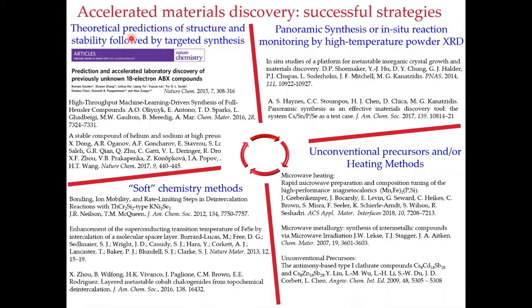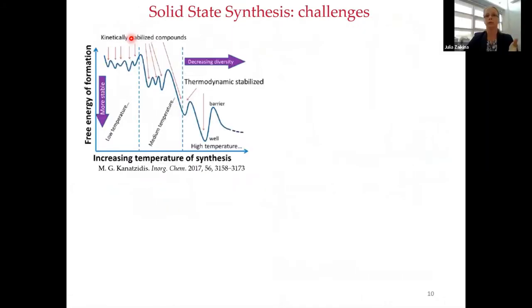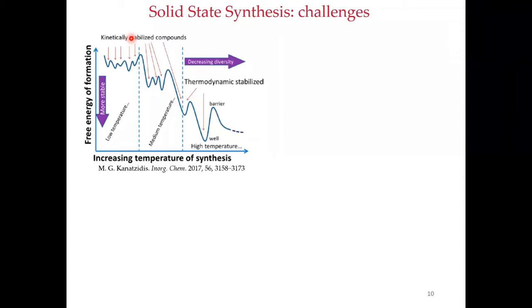And the challenge here is that in general, we do need high temperatures for solid state synthesis, because we start by mixing several solids, and the diffusion is very slow. So by increasing the temperature, solids transform to liquids or sometimes to gas phase. So this increases the diffusion, this increases the rate of the solid state reactions.